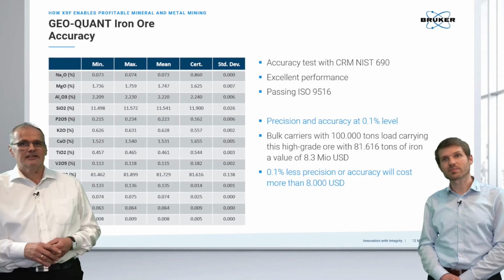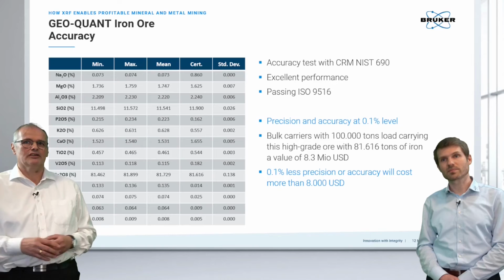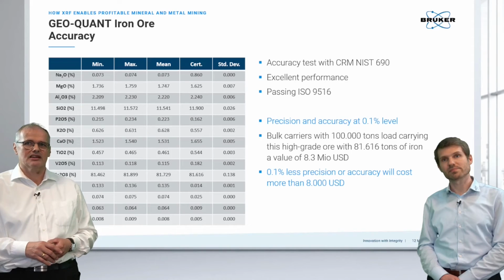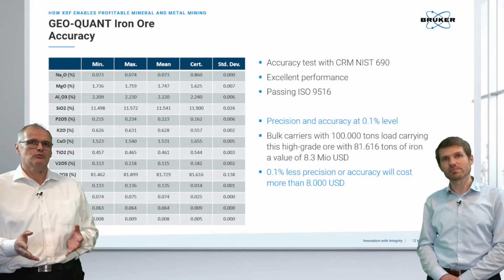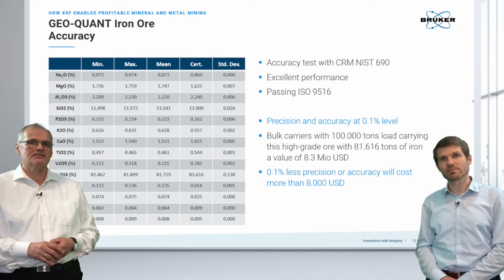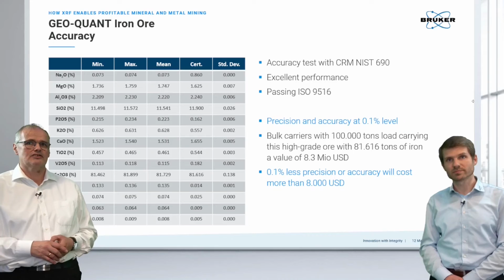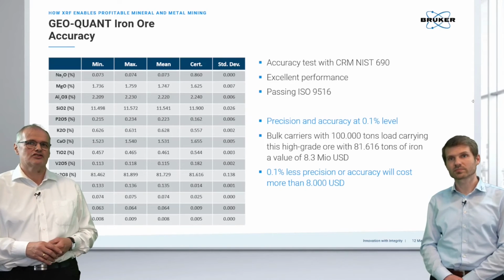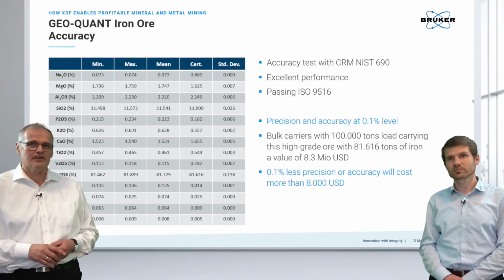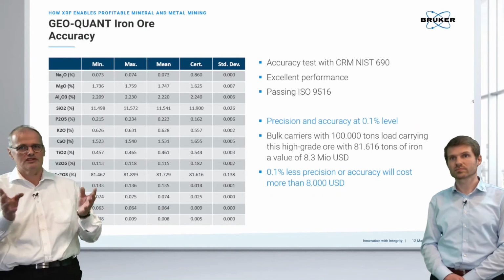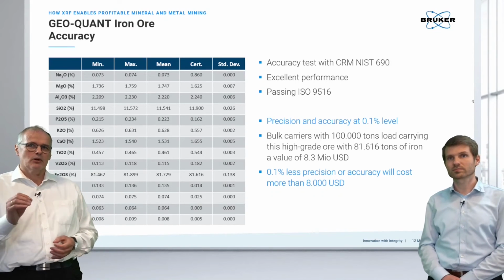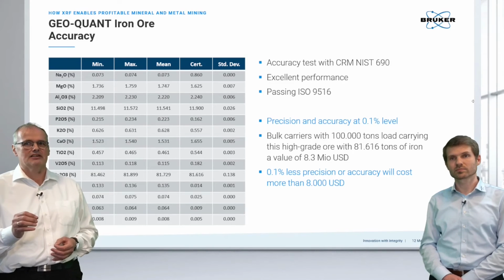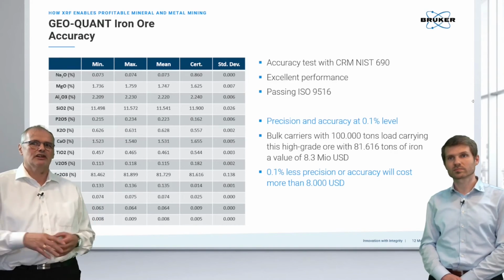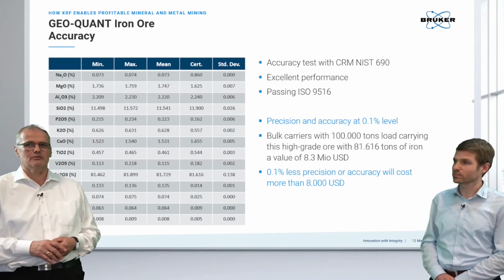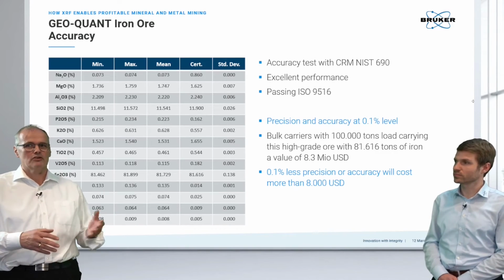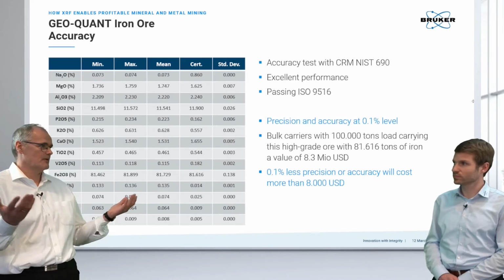Yeah. And those are the data we achieve looking at the accuracy test with NIST 690. We can see when we are diving into the table, looking at the min, max value, the mean value, and comparing this to the certified value, that the standard deviation is pretty small, in a lot of cases below 0.0 or 0.1%. And when we think about the precision and accuracy level, 0.1%, when we have a bulk carrier with about 100,000 tons load carrying high-grade ores, we talk about 80,000 tons of iron with a value of something like $8 million.